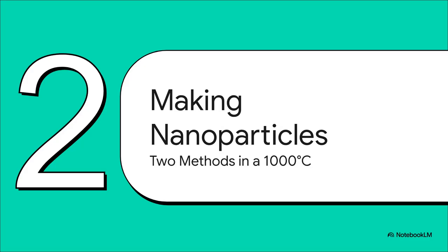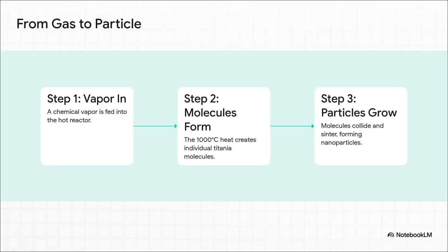Now, you have to understand, making these custom nanoparticles, it is not like baking a cake in your kitchen. We're talking about a furnace heated to a blistering 1,000 degrees Celsius. And as we're about to see, how you add the ingredients to this crazy hot furnace turns out to be incredibly important. The whole process is kind of like creating microscopic dust from thin air. First, a chemical vapor with titanium in it gets fed into the furnace. The insane heat breaks it down into individual titanium molecules. Then, those molecules start bumping into each other and sticking together. That's a process called sintering, and they build up into these tiny nanoparticles.